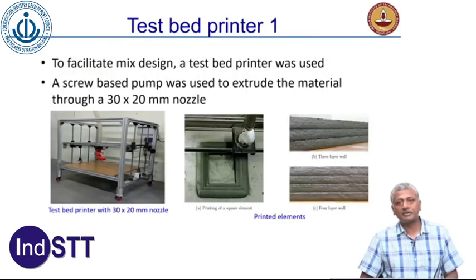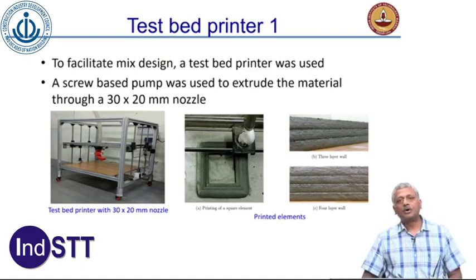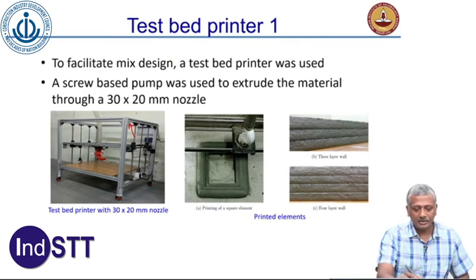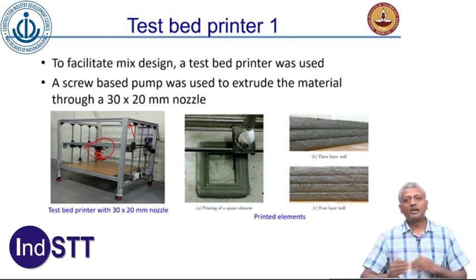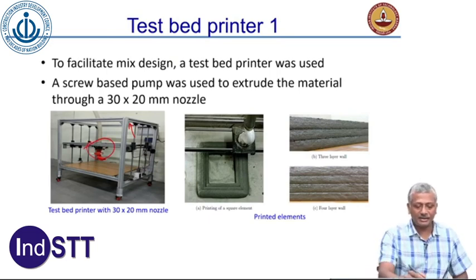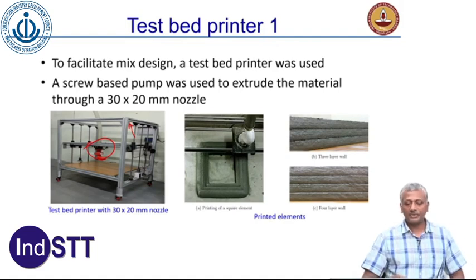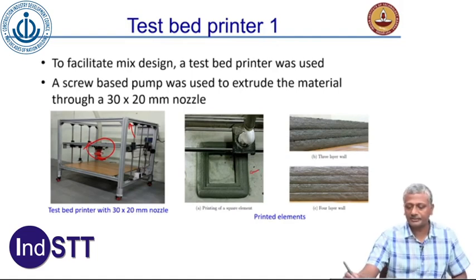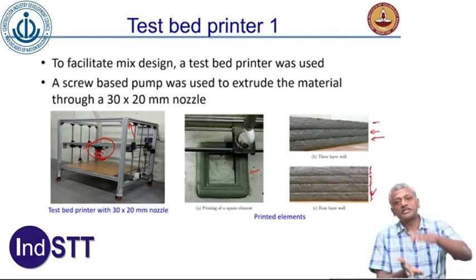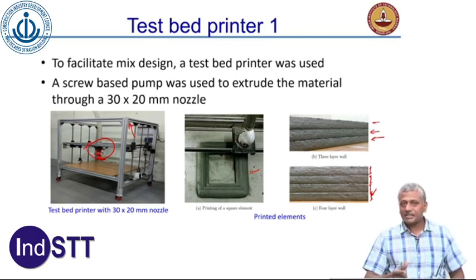So this is the example of the testbed printer, fairly simple. All it has is a gantry which is very small. Okay, you can see that this is a gantry, and you have your movable arm which is moving around on this gantry, and the nozzle attached to the movable arm. With this nozzle we have printed square elements like this, also wall elements which are having different layers. What you are able to clearly see is that each layer has a perfect thickness. That means the layer below has not got compressed because of the weight of the layers above, and that's because of a proper design of the material itself.